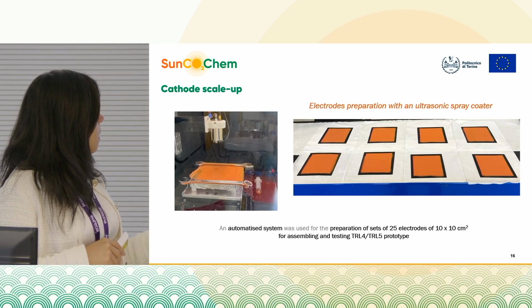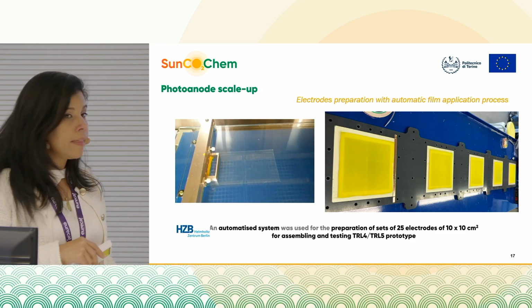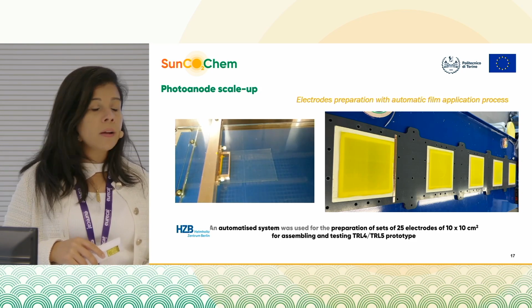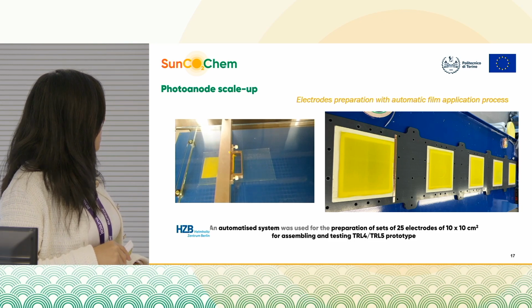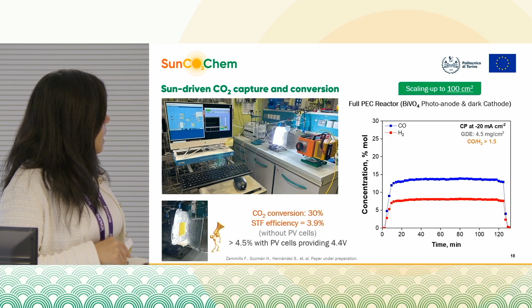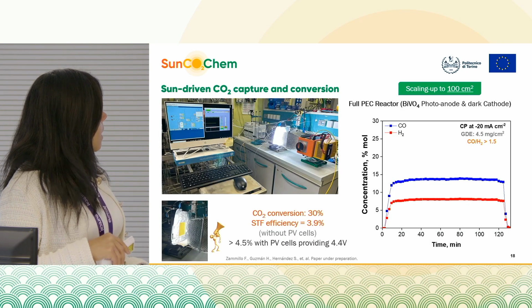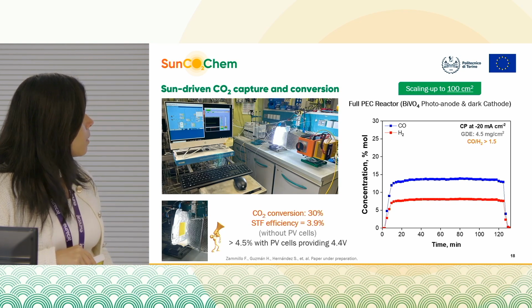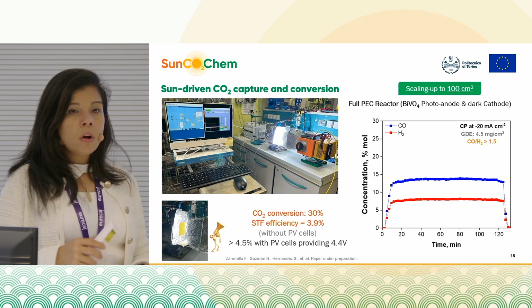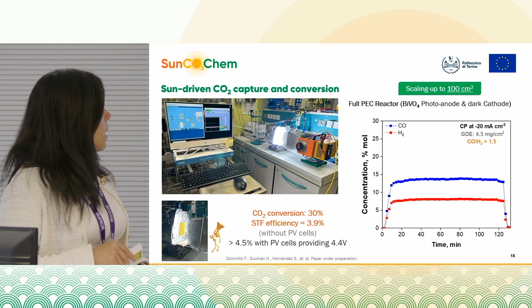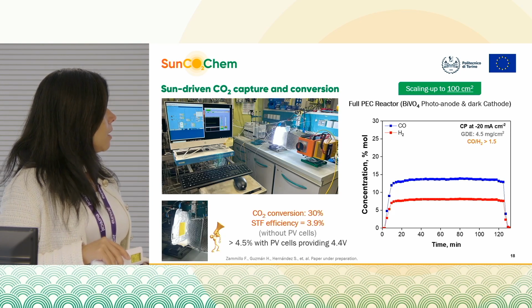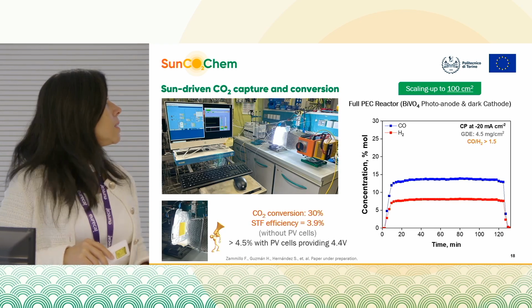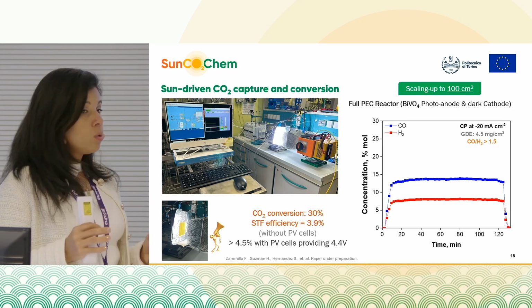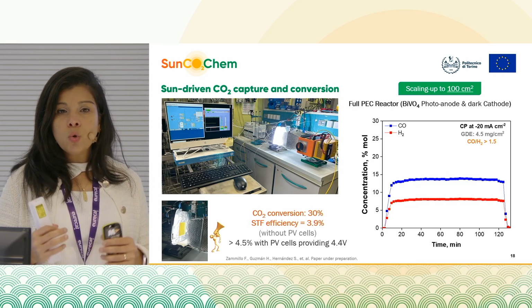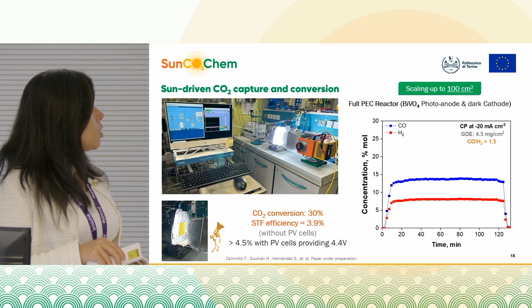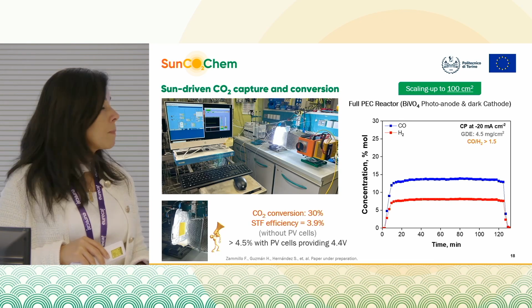And Helmholtz Zentrum Berlin also scaled up the process of preparing the bismuth vanadate photoanodes with an automatic film deposition technique. And in our labs, we tested the TRL4/TRL5 prototype exploiting these two photoanode and cathode, and we demonstrated a very good stability of the system, and we fine-tuned the process conditions to be able to obtain the CO2 to hydrogen ratio that was required in the project.